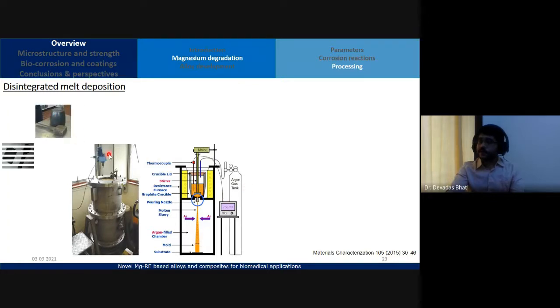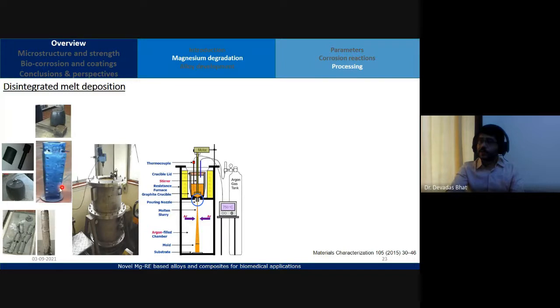This is the crucible that we have used. This is the mold that we have used, the stainless steel mold. Crucible is made up of graphite. All right. So this is the thermocouple, this is the motor, and this is the argon inlet. So the mechanism behind this is once the melt attains a particular temperature. So melting point of magnesium is around 660. We heat it 100 degrees Celsius above the melting point. We heat it up to 750. We also add other alloying elements that we require, and lower melting point. Barium, calcium. Calcium has melting point of about 840, I think.